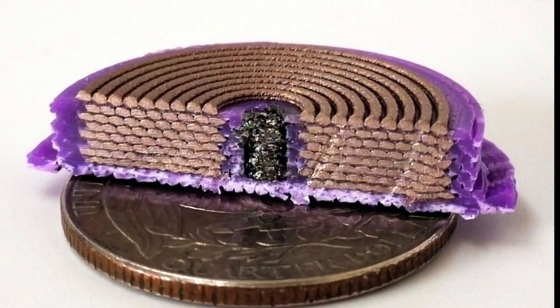Using the conductive material also posed challenges, since it would start melting and jam the nozzle. The researchers found that adding ventilation to cool the material prevented this. They also built a new spool holder for the conductive filament that was closer to the nozzle, reducing friction that could damage the thin strands. Even with the team's modifications, the customized hardware cost about $4,000. So this technique could be employed by others at a lower cost than other approaches.